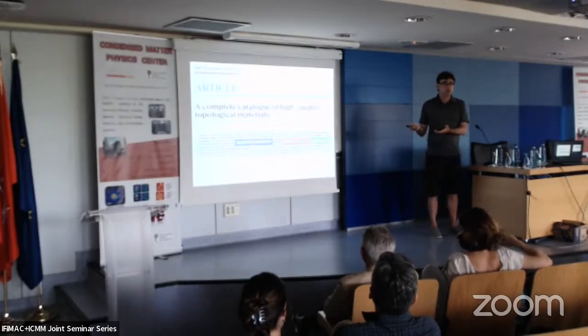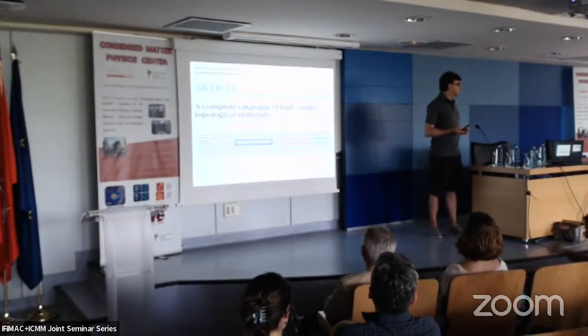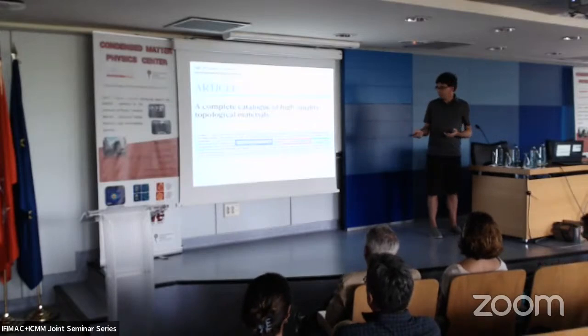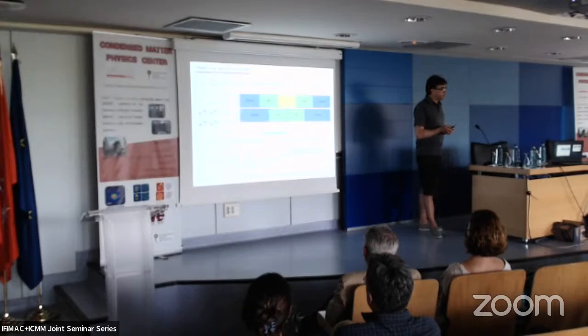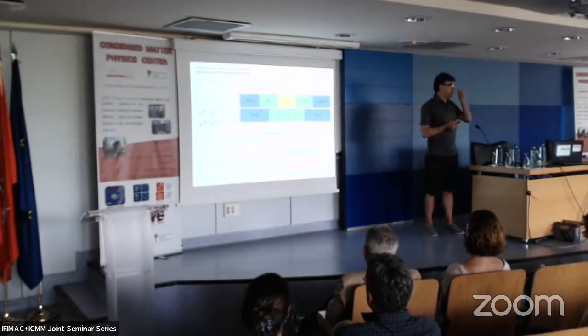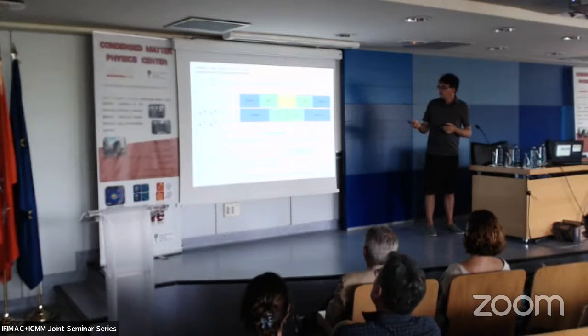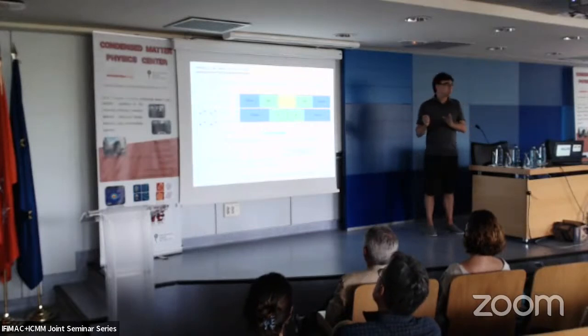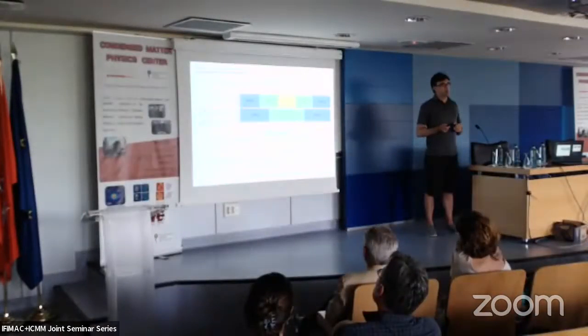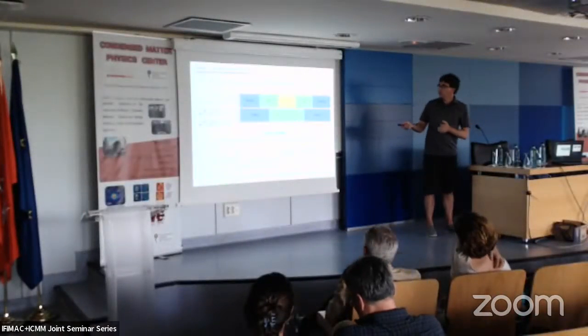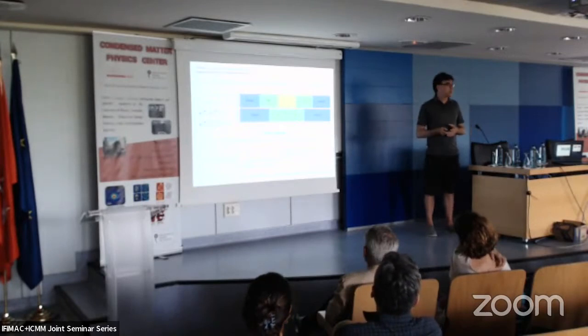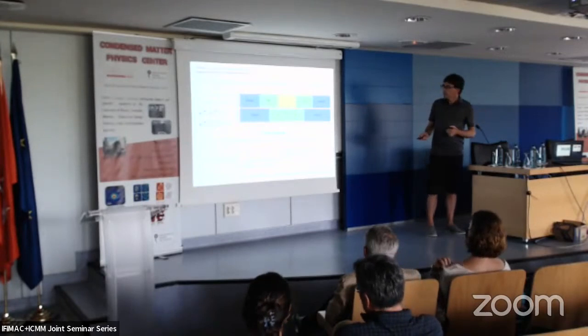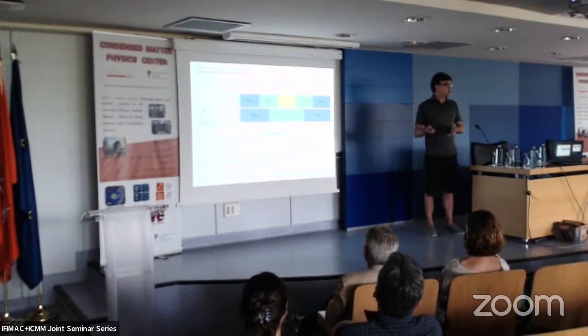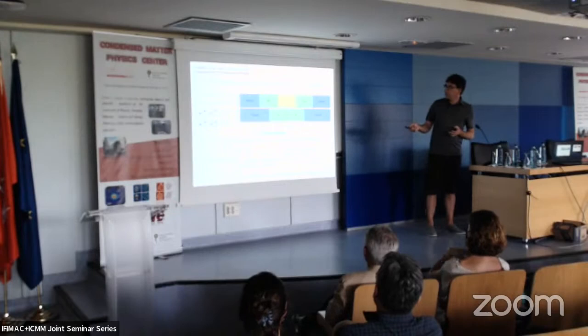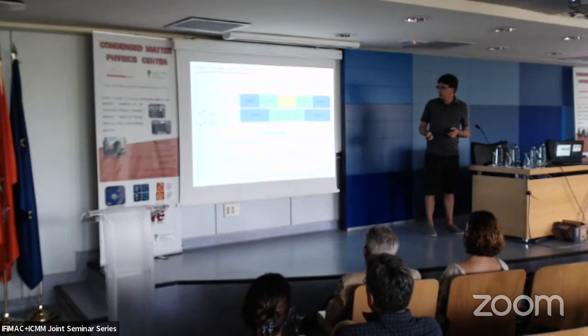So I mean, at this point now we can just look it up. But of course, this is not possible for amorphous materials, for non-stoichiometric materials. There's no catalog for that. So we have to do something about it. And the thing to do is we have done some theory. Initially, we are doing just some simple model at this point. We call it the Wilson Dirac lattice model. This is just a simple model that recreates the transition from trivial to non-trivial, from topological insulators, etc., just on the basis of a single mass parameter. And then we have generalized this to introduce disorder. So basically, instead of just having a simple cubic lattice, we have a disordered lattice, a disordered model that is presented.